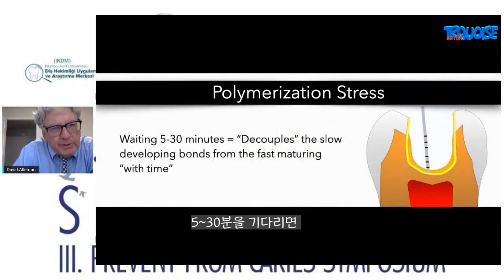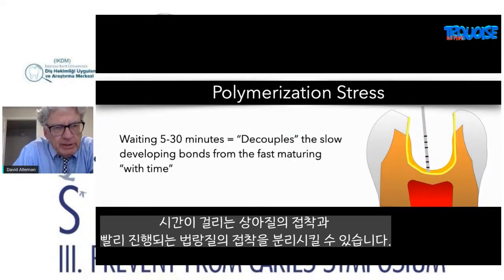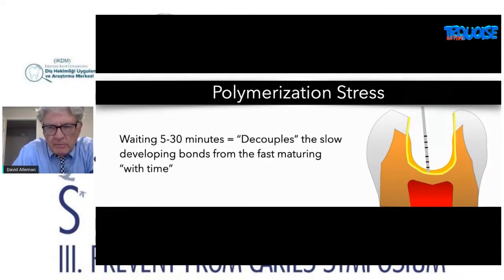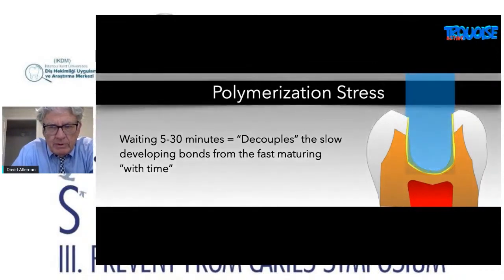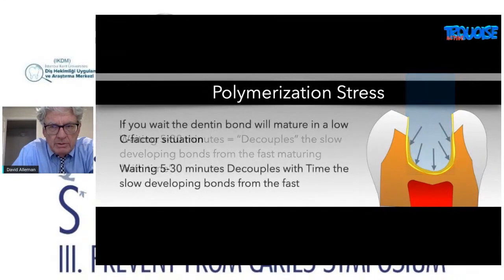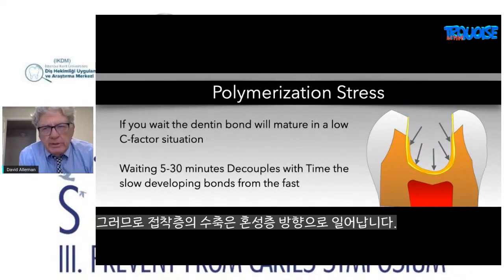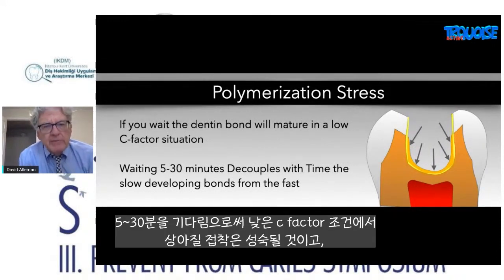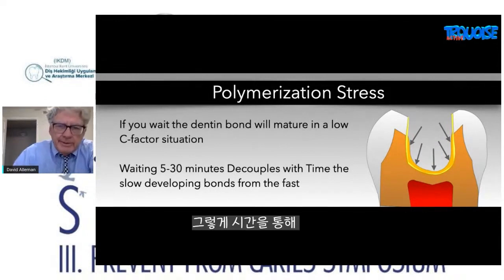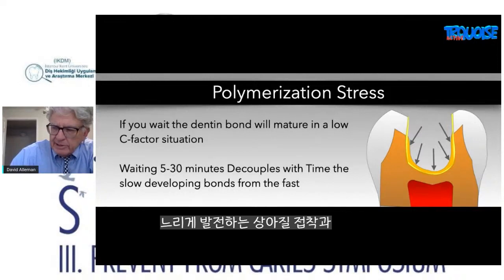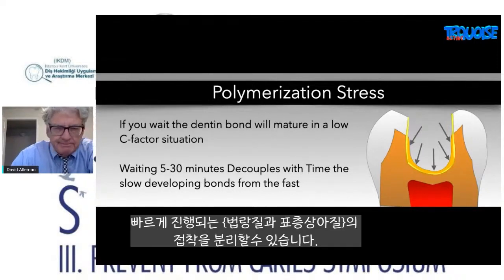So by waiting 5 to 30 minutes, you decouple or separate the slow developing bonds that are in the dentin from the faster maturing bonds in the enamel. Therefore, the shrinkage of that layer goes towards the hybrid layer. So if you wait, the dentin bonds will mature in that low C factor situation. By waiting 5 to 30 minutes, you decouple with time the slow developing bonds from the fast developing bonds of the enamel and superficial dentin.